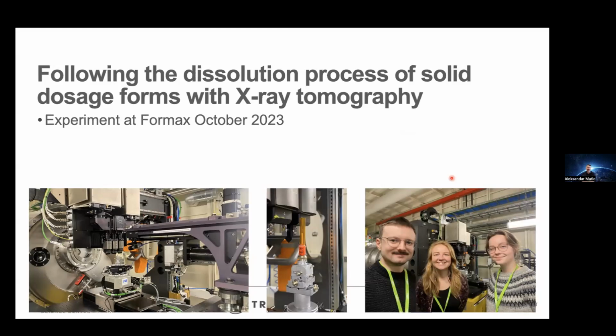So this was an experiment done at ForMAX in October 2023. So a very first test. So you can see here to the left, you see the imaging stations, the microscope, which is then recording the microtomography. And then you can move away this microscope, and then you can do SAXS. So Martina created a particular setup. You see here, she has a Kapton foil, which makes like a tube. And inside she placed her sample, which is this white, small spaghetti-like thingy. And then she could fill the tube with the dissolution medium, with the buffer medium. And then when she filled it, she could start the measurements and then look at the dissolution as a function of time. And you can see here, when you visit Kim, you will have this type of happy users at the experiment.